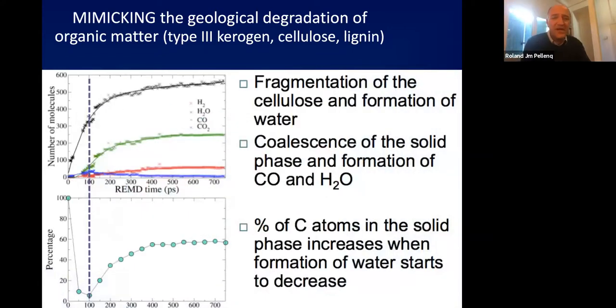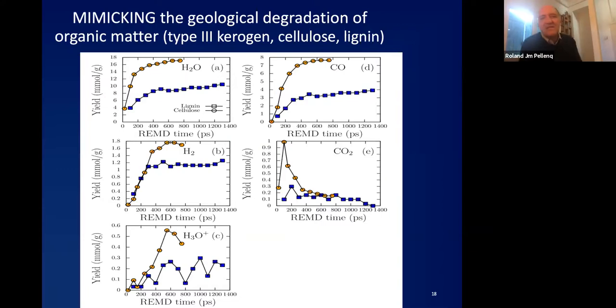All right, now we can try to analyze the different molecules formed. So let's start with the light ones. You see, as the time of the simulation moves forward, we can see the production of hydrogen, water, CO2, as I said, right? At the same time, after a decrease of the carbon backbone, you see the drop on the bottom plot, you have a regrowth of a phase made of carbon, right? This is the backbone growing up of things that will be, in the end, the porous kerogen, as we will see. Right, so then we can compare lignin and cellulose, for instance.